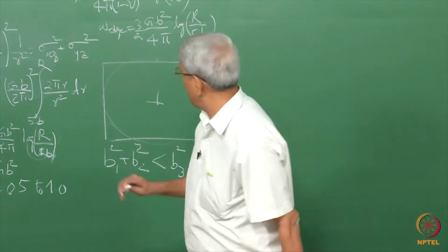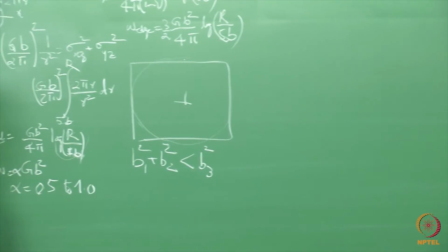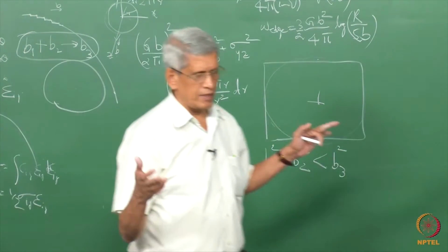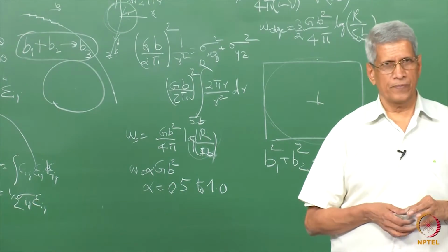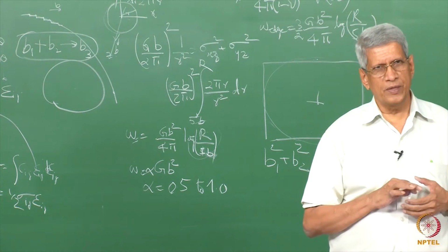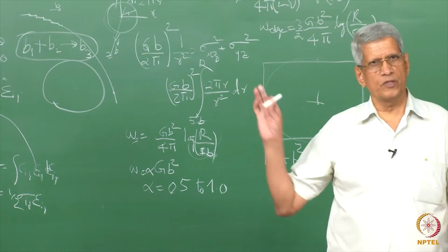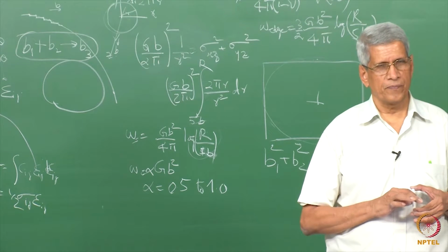Then we have to define this radius r. What is generally taken is that if a large quantity of dislocations is present in the sample, we find out the average distance, the separation between the dislocations, and take half of this to be the r. That is how this self energy is calculated.